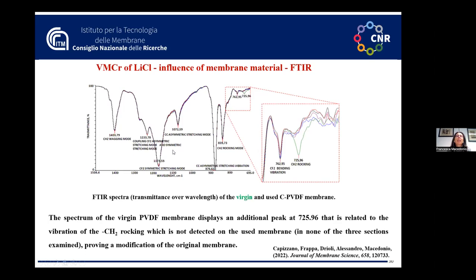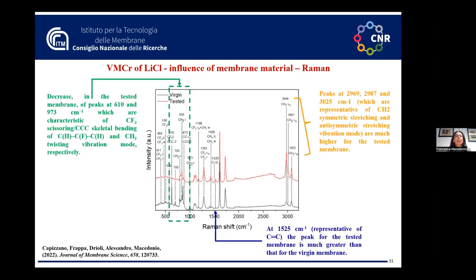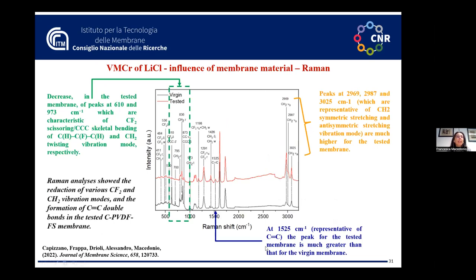What we can see here is the spectrum of the virgin membrane, the green spectrum, and the spectrum of the tested membrane. It seems that the spectra are identical, except for the peak at around 726, which is present on the virgin membrane but not on the tested membrane. And in fact, Raman analysis proved that in the case of the tested membrane, the red spectrum, we can see the formation of an additional peak, which is characteristic of a carbon-carbon double bond. This is a confirmation of the chemical interaction between the tested membrane and the lithium chloride solution.